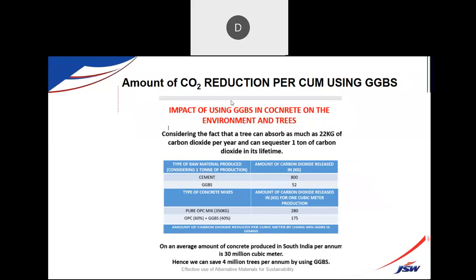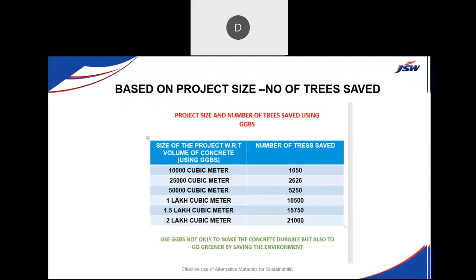A plant. Okay. When you are making concrete, using GGBS and replacing about 40% of the cement content, I'm talking about close to about 104 to 105 kg CO2 reduction per cubic meter. So if I'm using 20 cubic meter, then we're going to save 2 trees. If you're using 10 cubic meter, it's equivalent to 1 tree. That's how. So for smaller projects, I've given the statistics: